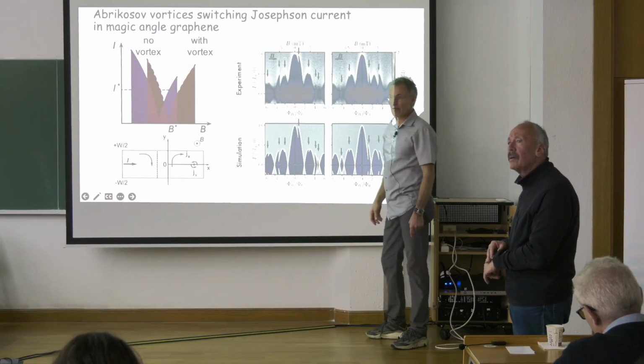And you had an image which was like a VI relation for a particular value of applied magnetic field. I think in the paper it was about 1.8 or something. And then you had that kind of VI curve, which was jumping between normal and superconducting phases. It's all the jumps between the normal and the superconducting phases, actually.